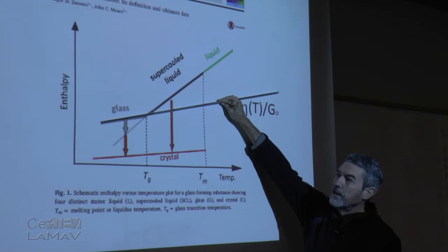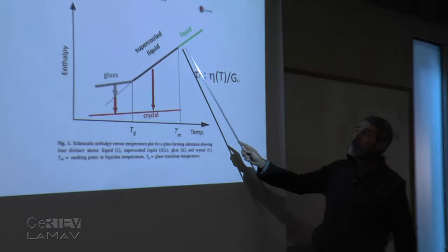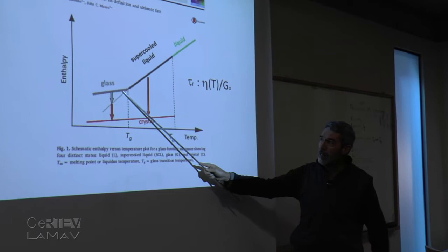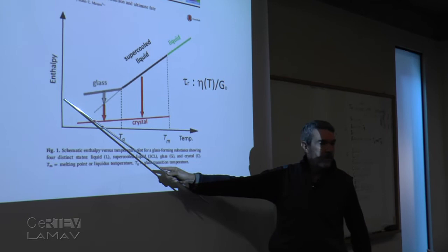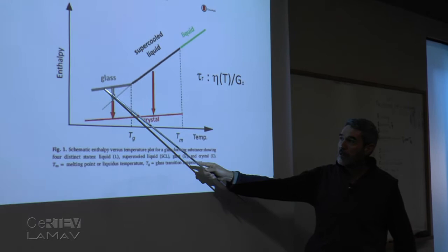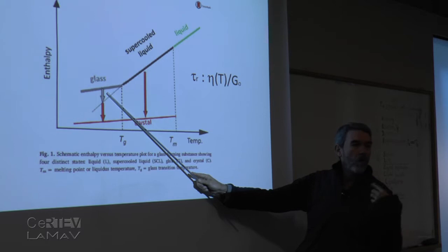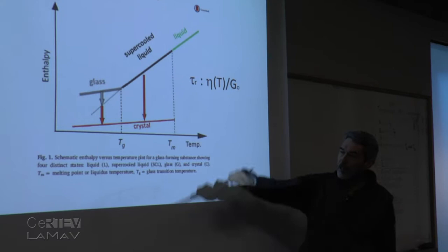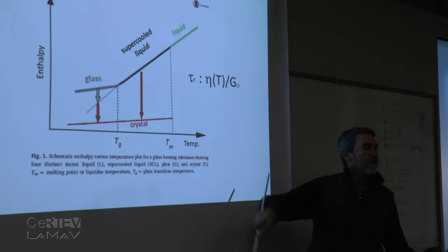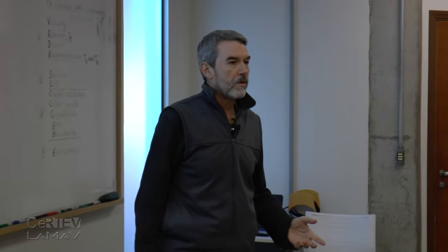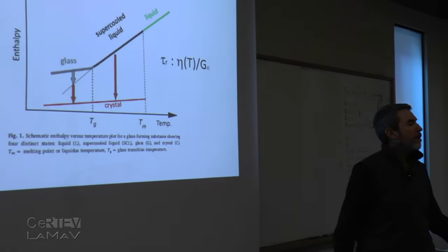Another way to see this is that, okay, for a given cooling rate, we came to this path here, made the glass, all the way down to room temperature. And then we heated this glass up to some temperature here below that TG. And wait, the glass will relax. And this relaxation time, of course, depends on the temperature. If we are here close to TG, say 5 degrees Celsius or so below TG, it will relax in minutes.